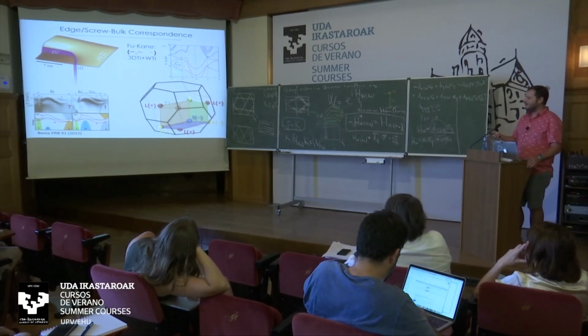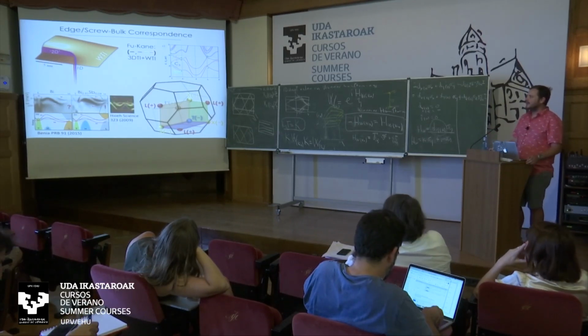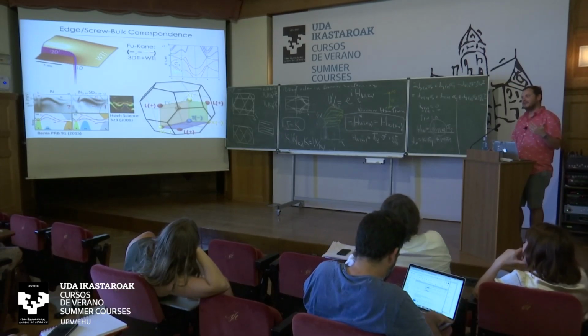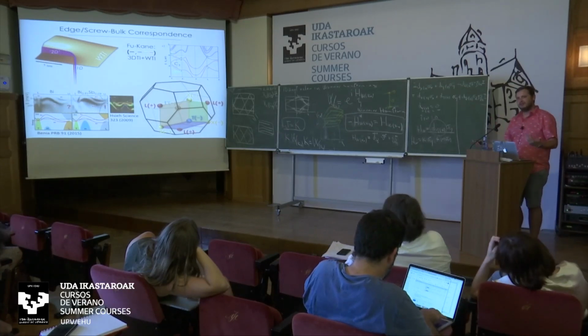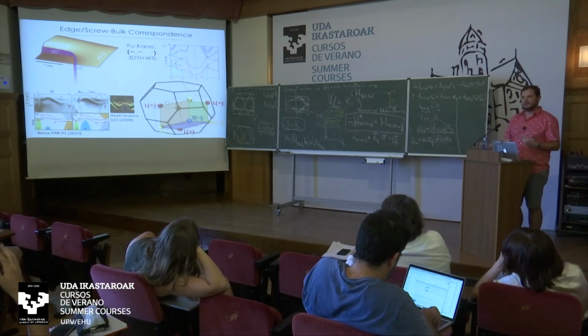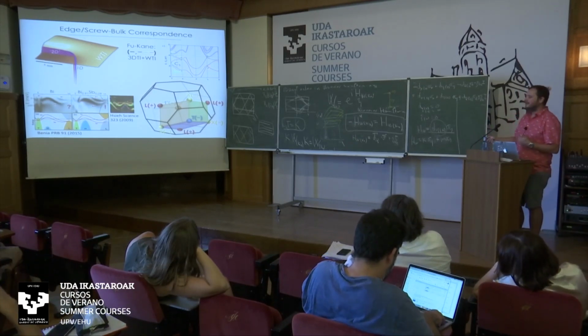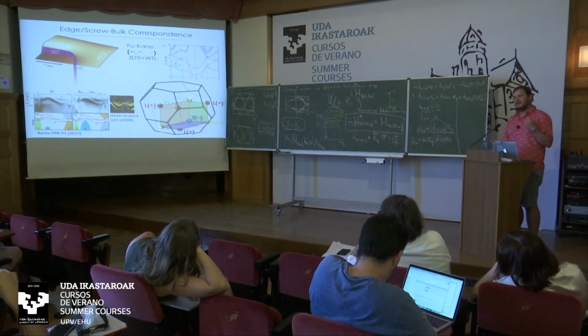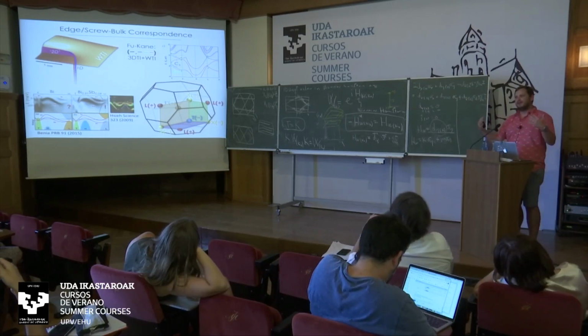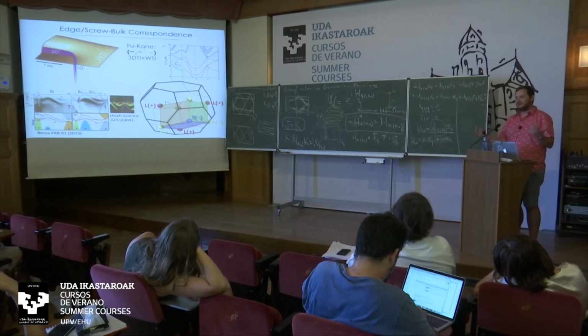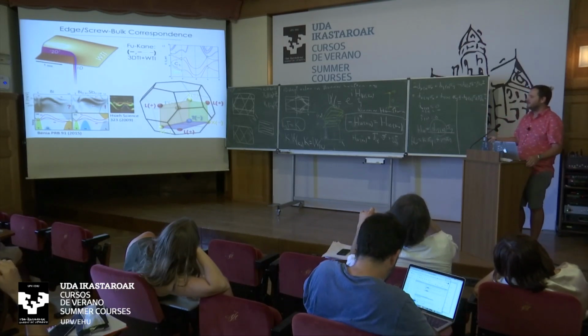What we believe, and our current DFT calculation actually supports that, is that basically bismuth is in the critical regime of the topological phase transition. So the sheer fact that the L gap is so small means that the topological properties start to emerge on the surface of bismuth.